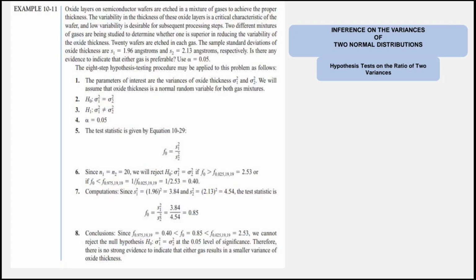The null hypothesis is variance 1 equals variance 2, with alpha 0.05. We use the test statistic in equation 10-29. In this example, the test statistic is S1 squared over S2 squared. S1 squared is equal to 3.84 and S2 squared is equal to 4.54, so the ratio is 0.85. Conclusions: since F sub 0.975, 19, 19, which equals 0.40, is less than F sub 0 equals 0.85, which is less than F sub 0.025, 19, 19, which equals 2.53, we cannot reject the null hypothesis at the 0.05 level of significance. Therefore, there is no strong evidence to indicate that either gas results in a smaller variance of oxide thickness.